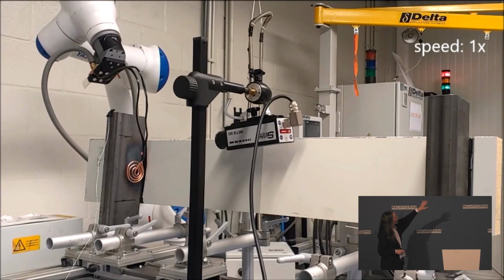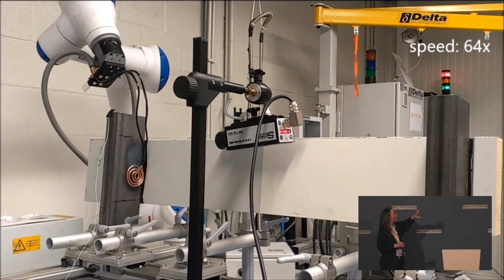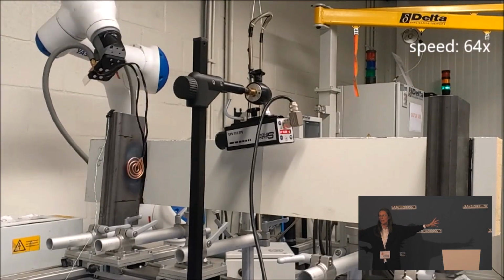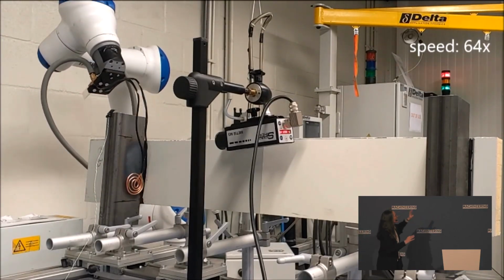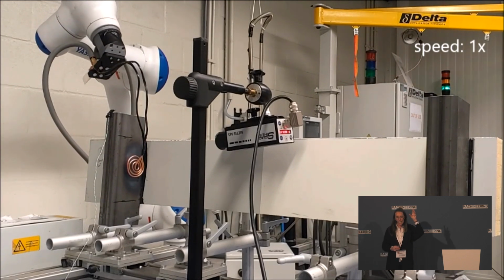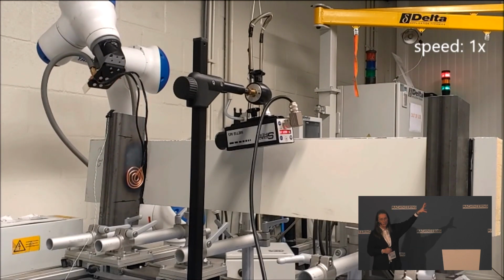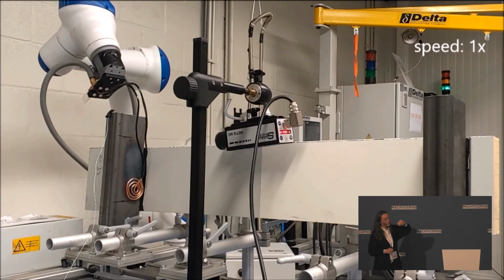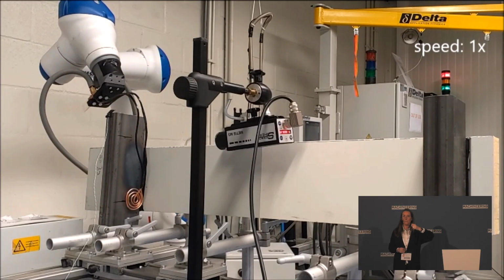What you see here is a cutout of that composite side panel. We didn't do the test on this, what is it, 10 meters wide bus. Our lab is not that big. So this is a cutout of 2 meters wide. And you see that the white panel is glued on the steel beams. The black line you see there is the adhesive, polyurethane adhesive, mixed with just a low percentage of thermal expandable particles. And we use inductive heating to heat up the steel beams. That heat is being transferred to the adhesive bond line and will make the thermal expandable particles swell a bit, just enough for the composite panel to come loose from the steel chassis.